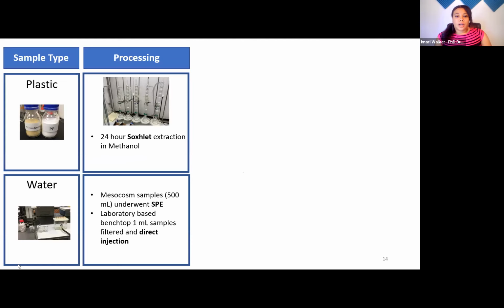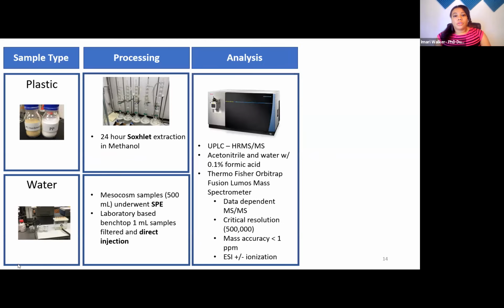So we had quite a bit of samples, including the water samples from the mesocosm and my own benchtop water samples, and extracts of the plastic itself to look for chemicals and try and identify some common trends over time. Analysis was done using our Orbitrap Fusion Lumos mass spectrometer, which allows us to get really strong mass accuracy, less than 1 part per million, and it gives us a really high resolution to identify down to 6 decimal points the masses that are present within our samples.